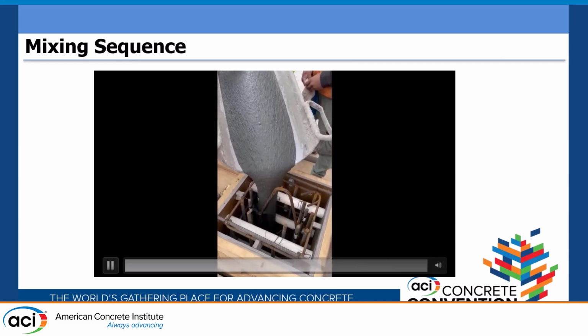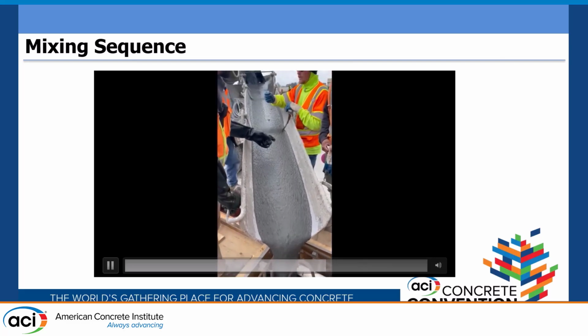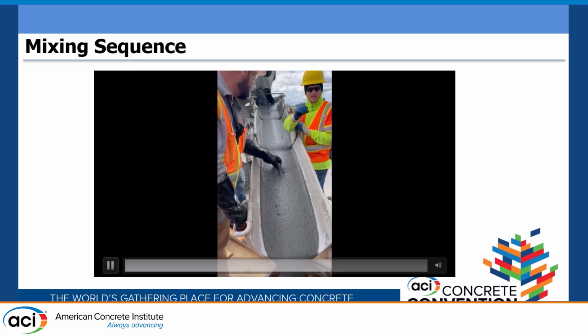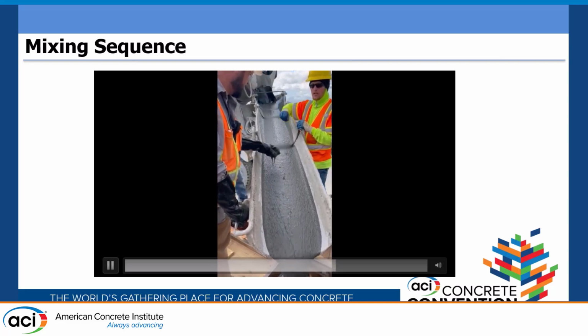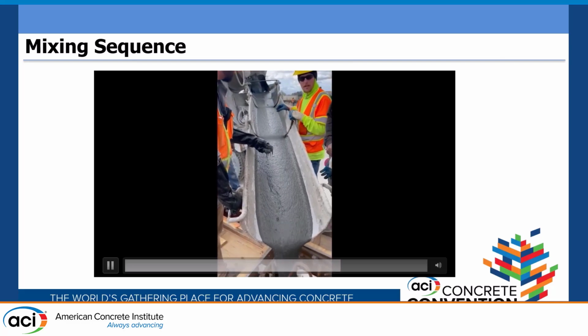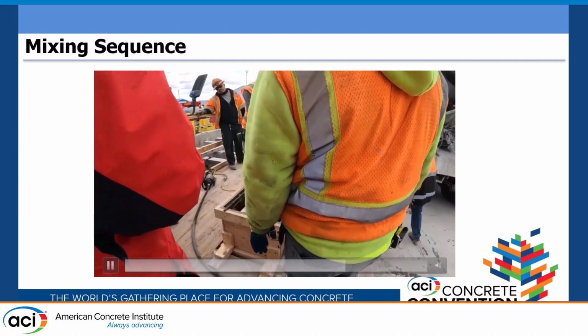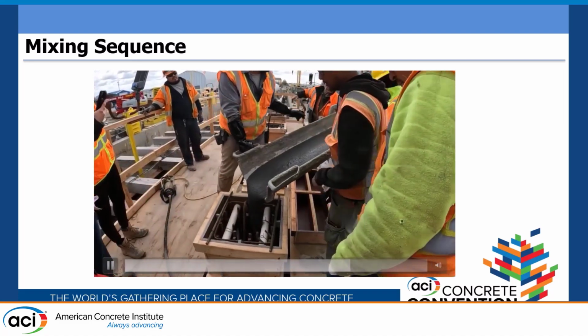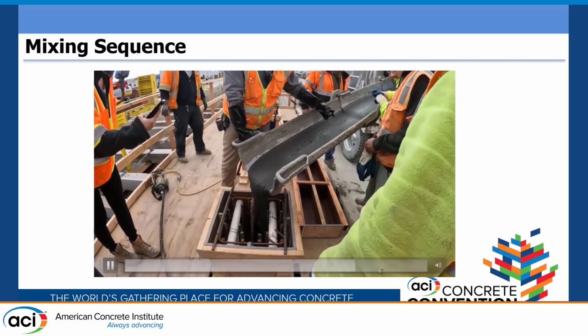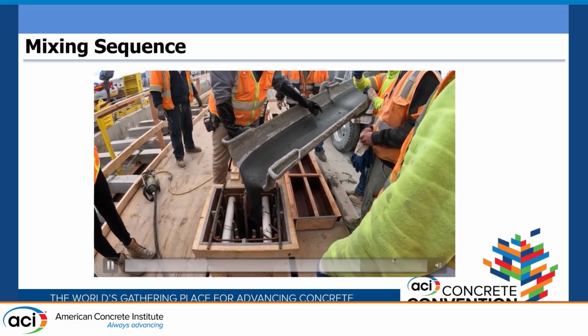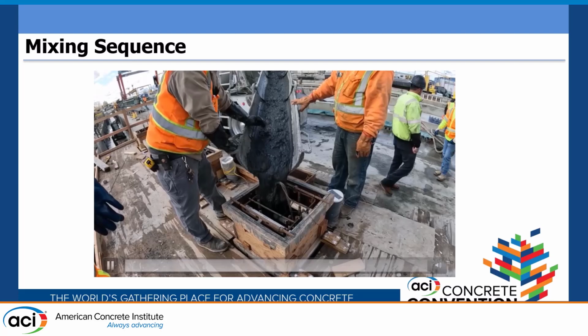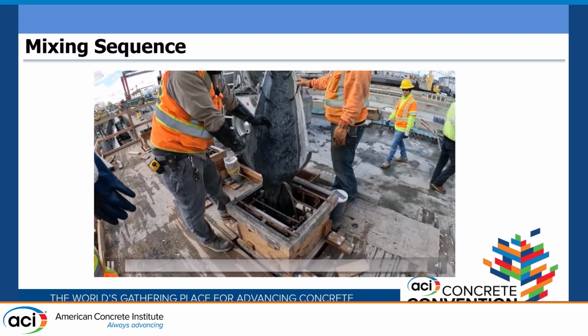It has a good flowability, around 8 to 9 inches. So this is another view when we're putting the UHPC on top of the loading head. If you can see, when it goes down, there's no reinforcement blocking it, so it just goes through. So this is the part that we saw from the recycled fiber.